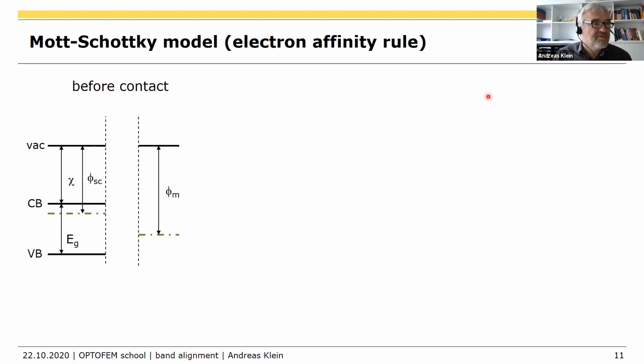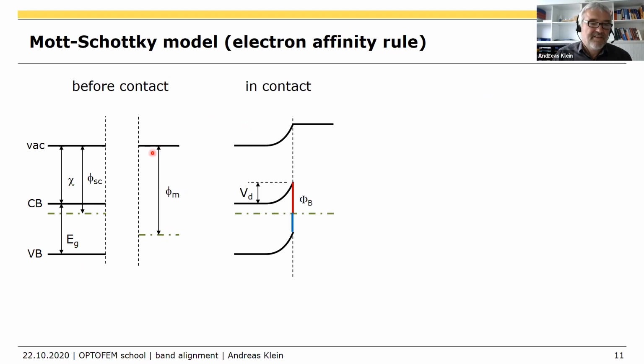So now if you follow the electron affinity rule, or the vacuum level alignment, you bring the vacuum levels into contact. But at the same time, you have to bring the Fermi levels into contact. And that's possible in semiconductors if you get a band bending in your semiconductor, a space charge region, because the Fermi levels are different. And the difference in the Fermi level is actually the magnitude of the band bending.